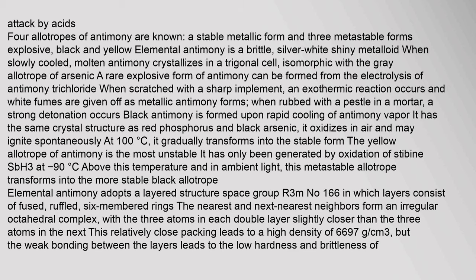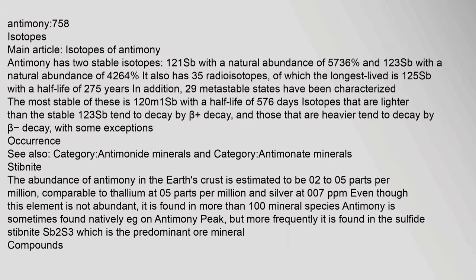Elemental antimony is a brittle, silver-white shiny metalloid. When slowly cooled, molten antimony crystallizes in a trigonal cell, isomorphic with the gray allotrope of arsenic. A rare explosive form of antimony can be formed from the electrolysis of antimony trichloride; when scratched with a sharp implement, an exothermic reaction occurs and white fumes are given off as metallic antimony forms. When rubbed with a pestle in a mortar, a strong detonation occurs. Black antimony is formed upon rapid cooling of antimony vapor.